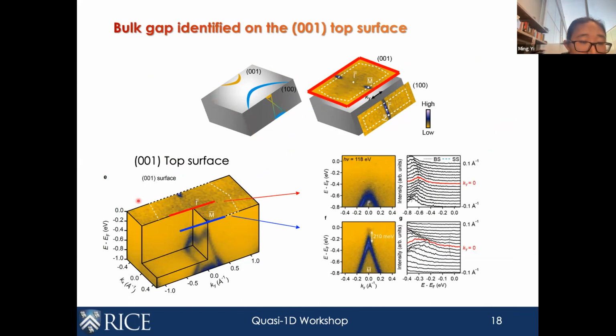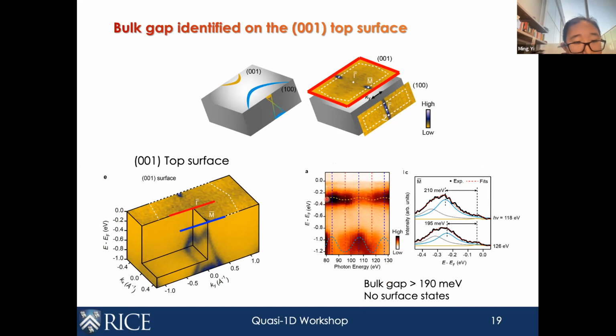Next, let's go through in detail what its topological nature is. So on the top surface, the 001 surface, again we can see a beautiful hole band top. These are bulk bands. Again, we can show this by varying the photon energy. This is the top of this hole band, and you can see that it varies periodically in kz, which demonstrates this is a bulk band. And furthermore, we can also fit the size of the bulk gap by taking individual EDCs here. And this shows us that the bulk gap varies from 195 millivolts to 210 millivolts, right? So that tells us the minimum size of this bulk gap is larger than 190, it's almost 200 millivolts. And within this gap, there is no topological surface state that we observe.